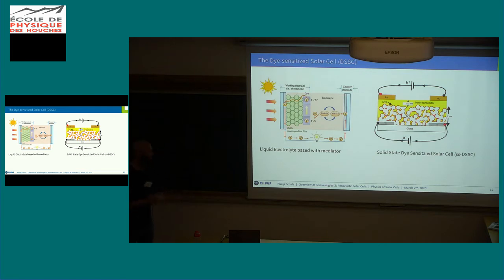So usually you want to capture light, and you do this by introducing a dye. So an organic molecule that has tailored energetic transitions to capture sunlight, generate an electron hole pair. The electron is transported away to this electrode, whereas you replenish electrons through the electrolyte that is oxidized and reduced in the cycle with a counter electrode. A big move forward, and this is now critical for the development of perovskites, was to have a solid hole transporter. So to not have the electrolyte, but a material, again an organic, that is permeable for ions and also can act as a hole transporter by itself.